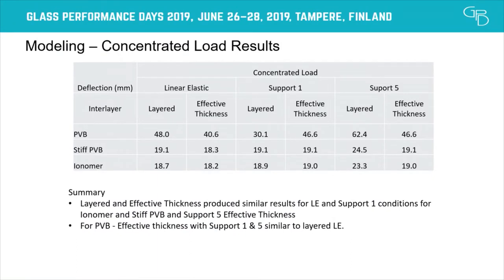So here are the results from the modeling study. This is for the concentrated load. For the stiffer interlayers, stiff PVB and ionomer, the values were pretty consistent except for the layered support 5, but all the others were about 18 to 19. For the softer PVB, it was a different story. The effective thickness with support 1 and 5 were similar to the layered linear elastic, but all the rest were pretty variable.